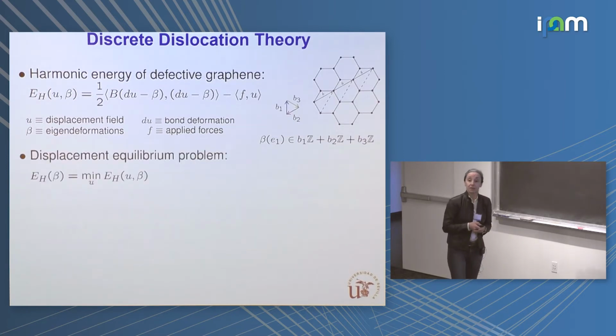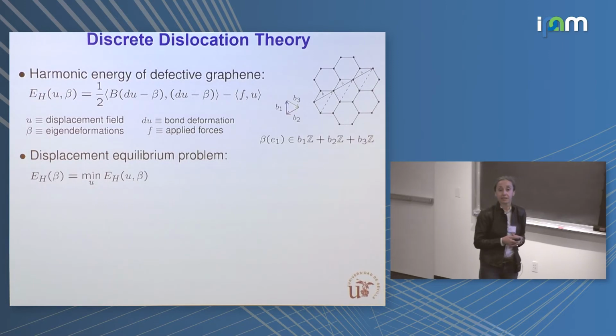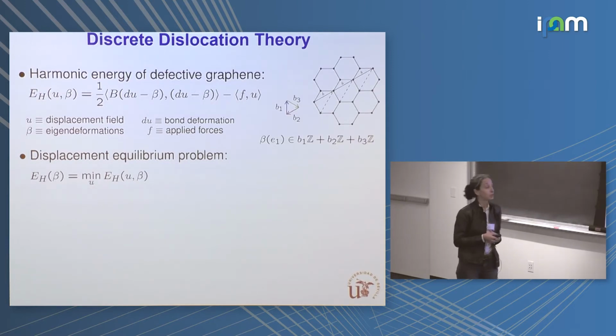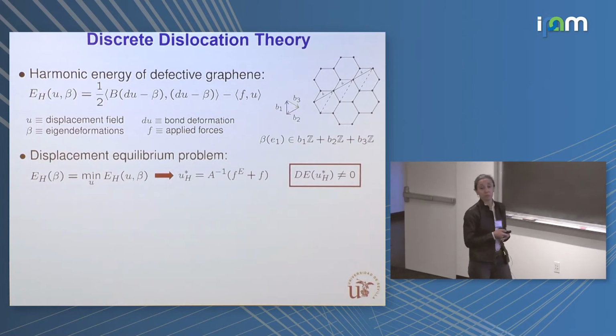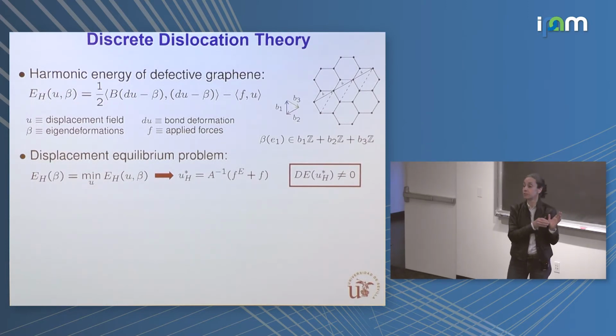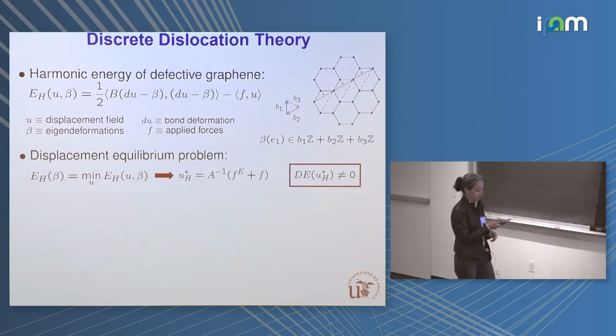So then we minimize this energy, and we obtain the configuration that corresponds to that kind of slip introduced within the lattice. Of course, because we are accounting here at this point only for the harmonic part of the potential, you have some out of equilibrium forces within the lattice, and this is accounting for the nonlinear effect.